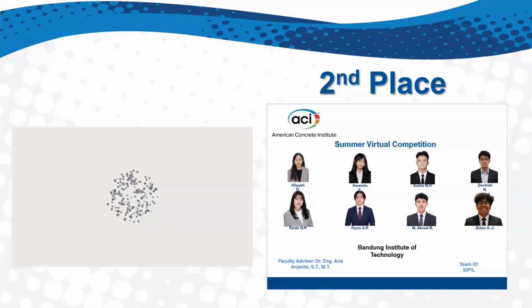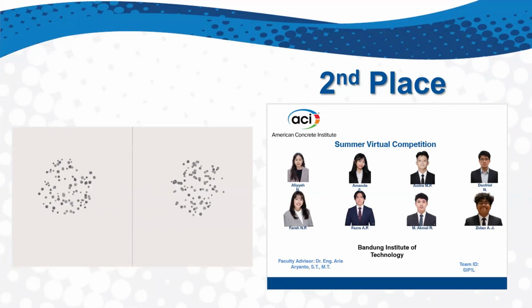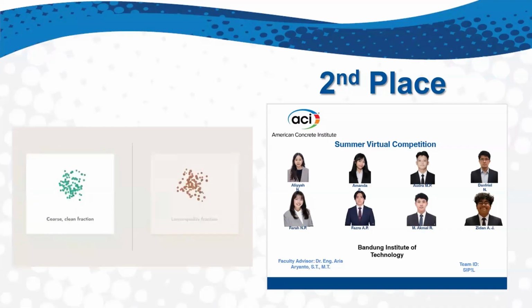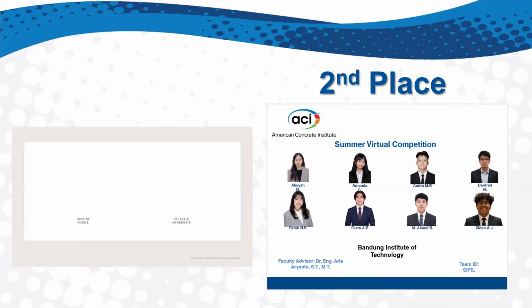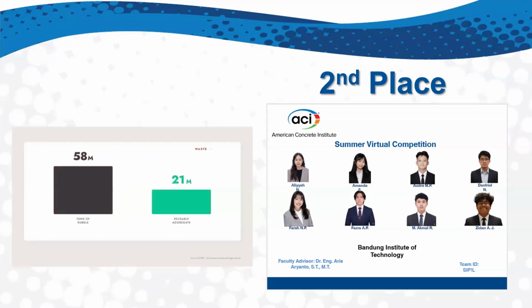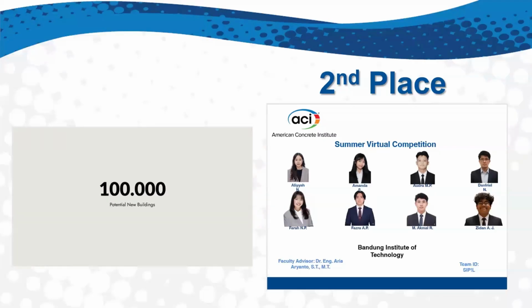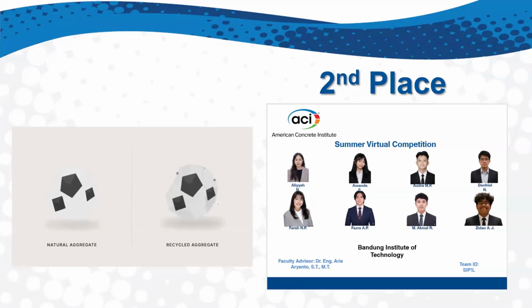Cleaner and coarse fractions are recycled into new concrete, and the lower quality fractions are used for other concrete-based goods. From those 5 disaster sites, we could recover 21 million tons of usable RCA. That's enough to reconstruct nearly 100,000 new buildings. But RCA has a weakness. Residual mortar stays attached to its surface, making it more porous, more absorbent, and weaker than natural aggregate.